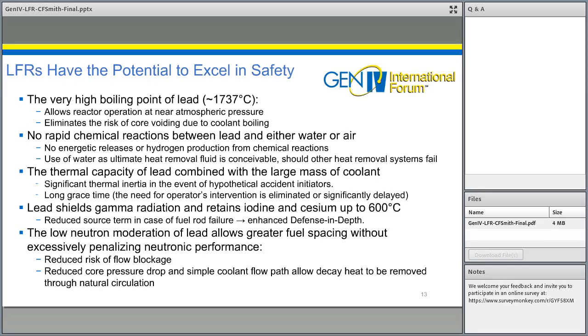To summarize this part of the discussion, lead-cooled fast reactors have the potential to excel in safety for reasons outlined on this slide. First is the very high boiling point of lead. As I said before, 1,737 degrees centigrade, or for lead bismuth eutectic for that matter. And this allows reactor operation at or near atmospheric pressure, and it virtually eliminates the risk of core voiding due to boiling of the coolant.